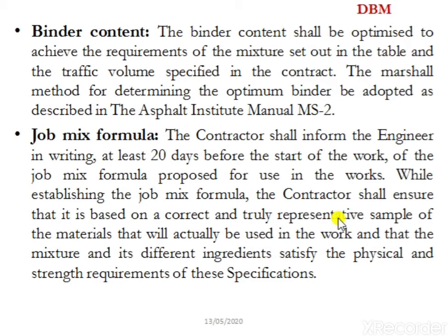The modified Marshall test by 150 mm diameter mold as specified in MS2 shall be used. When the modified procedure is used, the minimum stability should be multiplied by 2.25 and minimum flow should not be less than 3 mm.